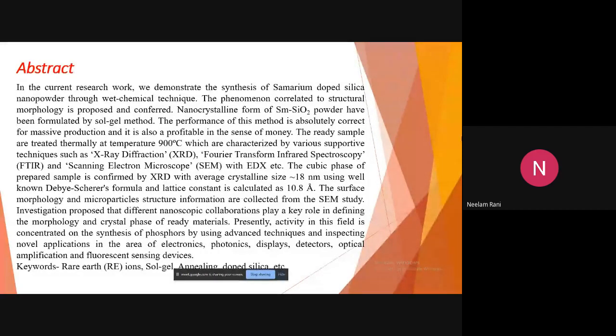Here we used two samples. First is the as-prepared, or we can say the grown sample, which is prepared at room temperature, and the second one is annealed at 900 degrees Celsius. The characterizations were performed with different techniques such as XRD, X-ray diffraction, Fourier transform infrared spectroscopy, and scanning electron microscope, SEM, joined with EDX, energy dispersive X-ray spectra.